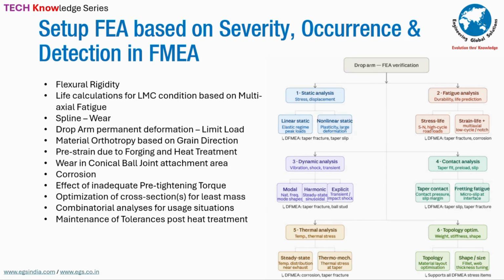So instead of doing a simple static analysis, which doesn't give you a whole lot of things, I'll give another example. Years ago, we were working on high-speed bearing testing. High-speed bearings are 70,000 RPM to 1 lakh RPM, 1,10,000 RPM. We were using a friction disk. The friction disk was rotating at 70,000 RPM. Typically, when a disk rotates at 70,000 RPM, we expect the hoop stress, the tangential stress to be high, right? No, the stress at the center was highest. Why? Because it was pulling the material from the center towards the edge. So finite element analysis is a confirmatory tool. People try to use it as a diagnostic tool. No, the diagnosis still lies with you.